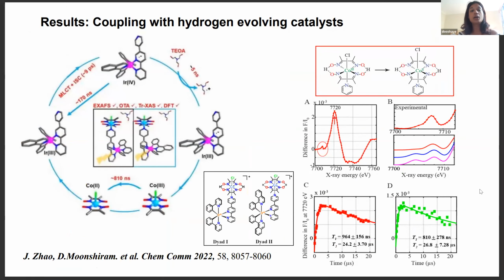More recently, we coupled iridium-based complexes with the typical cobaloxime proton reduction catalyst in a dyad fashion. And specifically, we studied iridium complexes with phenylpyridine ligands, as well as isoquinoline ancillary ligands. And interestingly, the iridium complex with phenylpyridine ligands showed more photoreduced cobalt(II) upon photoexcitation in comparison to its isoquinoline counterpart.